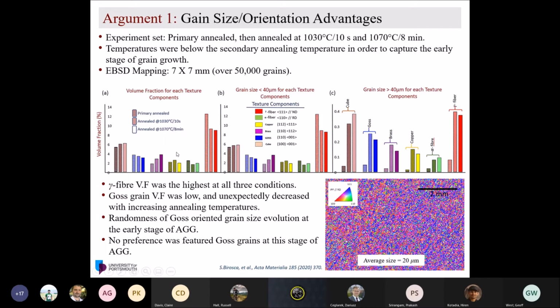Now, if you look at it, the Goss grain doesn't have a higher volume fraction than any of the other orientations in the sheet, and I'm counting about 50,000 grains. In fact, cube has a higher volume fraction than Goss, except the gamma fiber, which is highest in all three conditions. So Goss grain volume fraction was low, and it even decreased with increasing annealing temperature. We also saw this randomness in the Goss grain size distribution within the sheet.